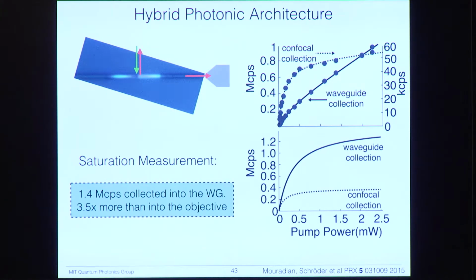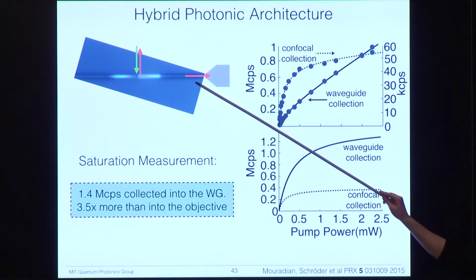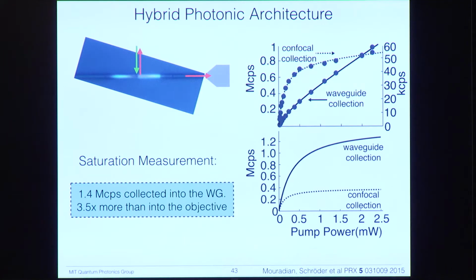So to validate our system, we did a few measurements. This is first a saturation measurement, where we increase the pump power. This is the power of the 532 nanometer light. And we collect light both through a standard collection system, through an objective from the top, and also through the waveguide. Here is the raw data, and here is after we account for losses in the system. What we're plotting here is collection into the objective and collection into the waveguide. So it's taking out the effect of the coupling from the waveguide to a fiber and from the objective into the rest of our optical system. So it's collection into the first optic. And you can see that there are 3.5 times more photons collected into the waveguide than into the objective. This is just a proof of principle concept, but it shows that this really allows for high rate collection of photons into waveguides.